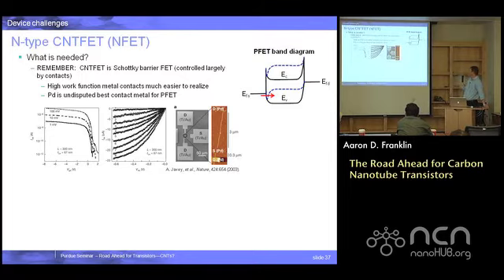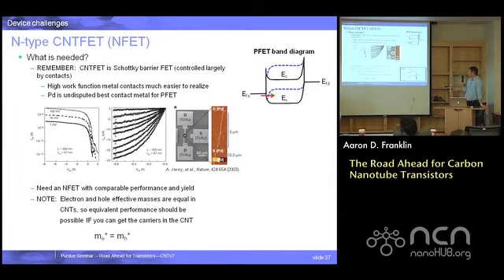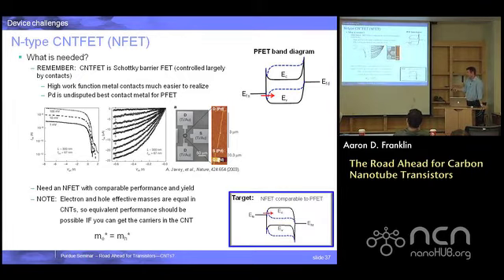Okay, and in this case, it shows the band diagram. Look at that, very simple picture of injecting with a high work function metal into the valence band with holes. So what I want to get to is a metal that can be as robust and compatible with processing to yield NFETs as opposed to the PFETs. One thing to keep in mind here at the physics transport level that a nanotube is very friendly about is the fact that the effective mass for the carriers is identical between the electrons and holes. There's symmetry in the dispersion relation. So this is great news for me. If I could just get them in there in the same way or similar way to the holes, then I can have electron transporting devices that are very complementary.